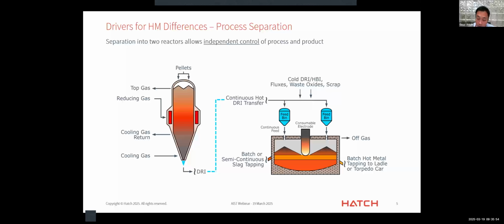Now, in the DRI shaft furnace, the preheating is done, the majority of the reduction and metallization is completed, and the hot material is charged into the ESF, where it undergoes complete reduction, metallization, melting, and separation into two different phases. While if you want to do all of these processes inside the conventional blast furnace, it requires very careful and simultaneous control of all of these various parameters to make your hot metal on spec.